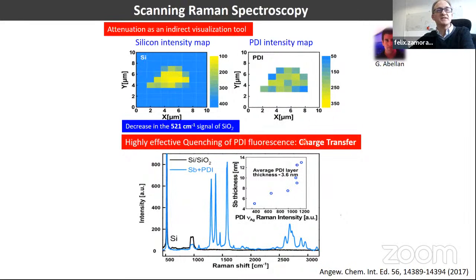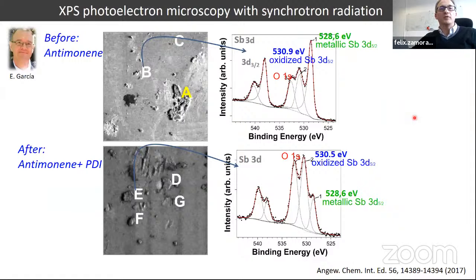Okay. So in order to confirm this charge transfer between the two components, antimony and the perylendiamine molecule, we carried out, in collaboration with Enrique García Michel, this complex experiment under synchrotron radiation, XPS in synchrotron. We prepared by micromechanical exfoliation different layers of antimony and located them on top of gold. Enrique called these layers A, B, or C. Here I show you one spectrum of the one named B. As you can see, from the initial material we have two interesting peaks: the one corresponding to metallic antimony, and the one corresponding to a kind of antimony trioxide.